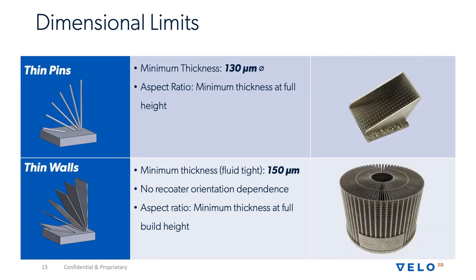So as I mentioned before, we're able to achieve more intricate geometries, and control them more precisely and more continuously, as a function of the advanced process control and application that we have, but also the recoater, like I mentioned. Structures like these thin pins are extremely delicate, and with conventional systems, once they reach a certain aspect ratio, the subtle force of the recoat mechanism is too much, and it starts to push them over. With the VELO system, if you wanted to print minimum thickness, 130 microns, you can print it the full height without any distortion, meaning you can print it 400 millimeters tall if you wanted to. So you've got the freedom that others don't when it comes to these thin pins.